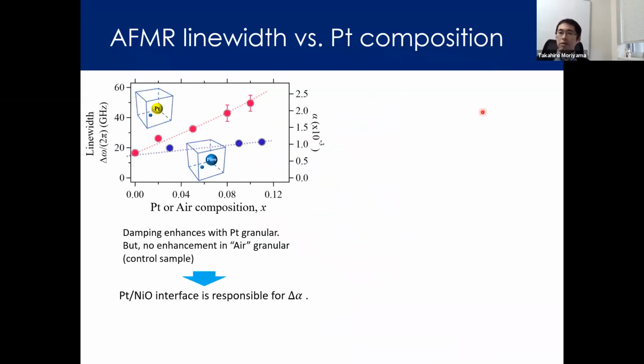So as a control sample, we also measure the sample with air holes instead of platinum granules, and see the damping does not change much in this case. So we therefore can conclude that the platinum nickel oxide interface is basically responsible for this damping enhancement.